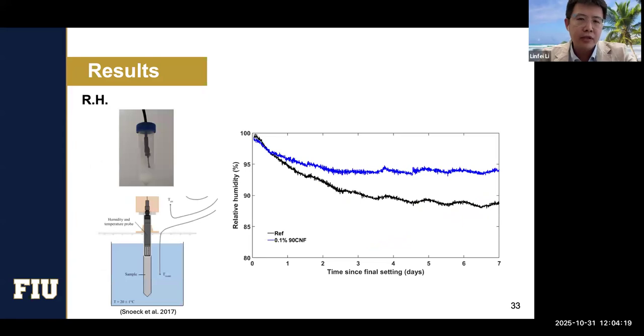And finally, that's another direct observation. For getting the relative humidity, because the relative humidity in your system is basically the trigger to generate the autogenous shrinkage, at the beginning we had a hard time because the relative humidity of the cement solution is very high. So most of the sensors cannot work, because the heat of hydration will generate a lot of vapor. That will damage the sensors or make them not very accurate.